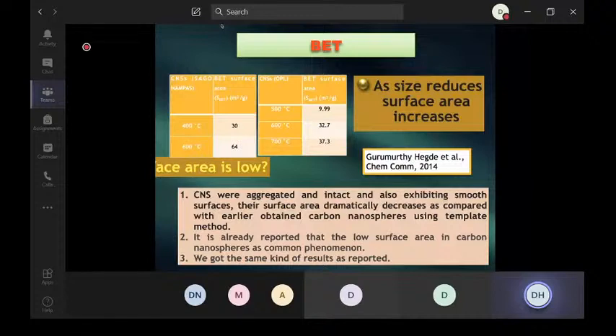Then again, we found out why such a difference in surface area takes place in the same material with different methods. Then we found that such carbon nanospheres always come as aggregations. They are not coming as a graphene layer where you can peel off one layer by one layer. Here they come as aggregated, and they are intact. They also exhibit very smooth surfaces. Working on bio-waste material based carbon nanospheres is extremely difficult. Whenever you measure such surface area, you always measure in aggregation. So that's the reason the surface area is always decreasing, because you are coming like an island of several molecules there. So it's not easy to measure the surface area of such bio-waste aggregated smooth surfaces.